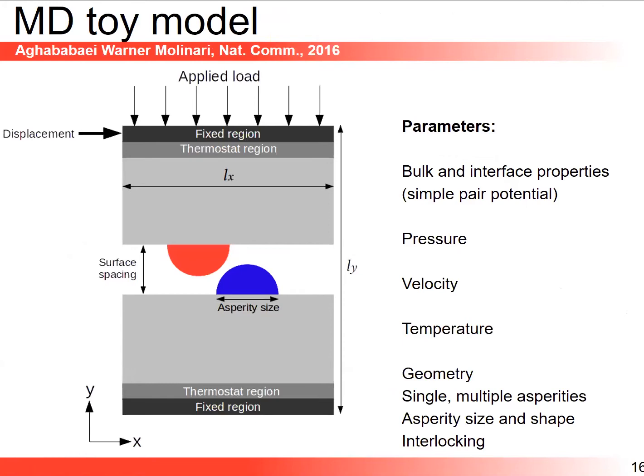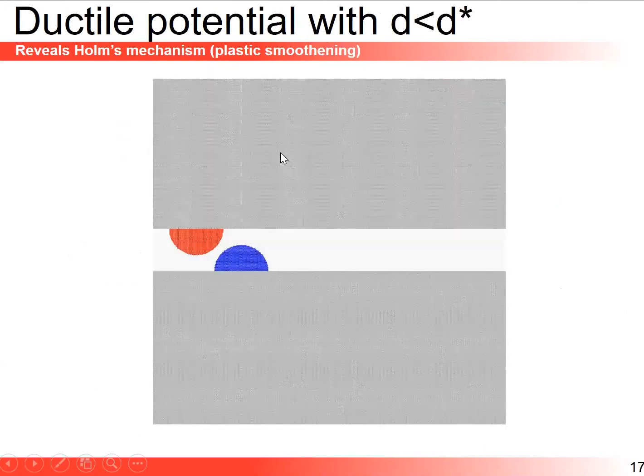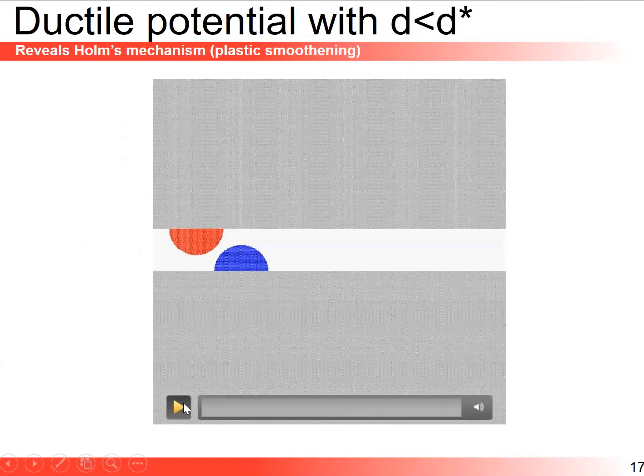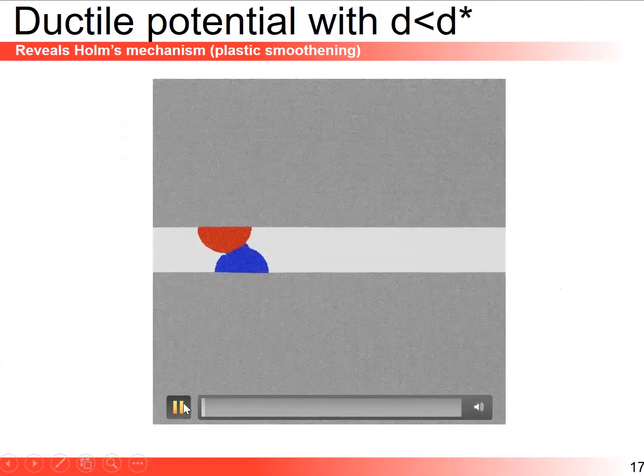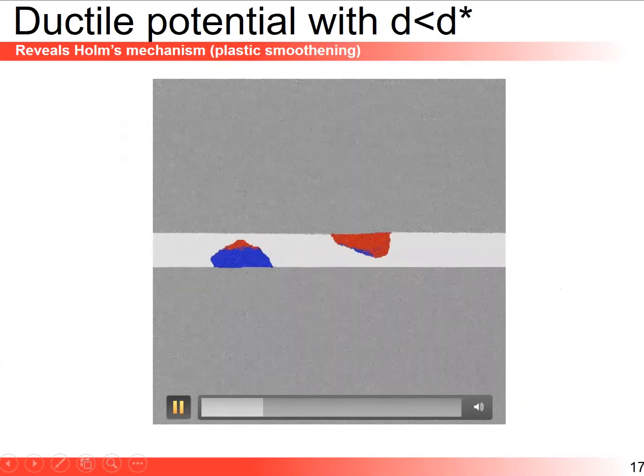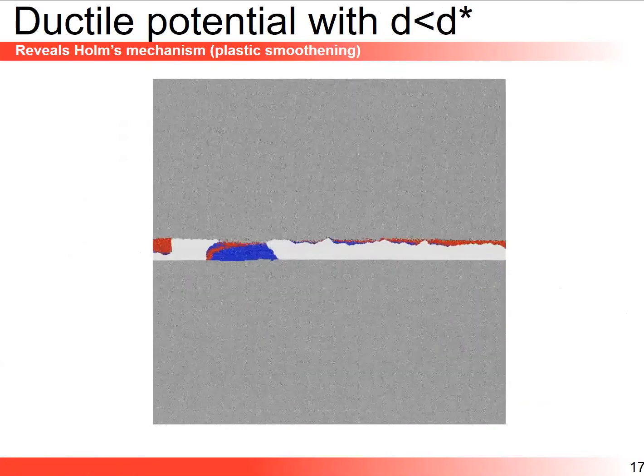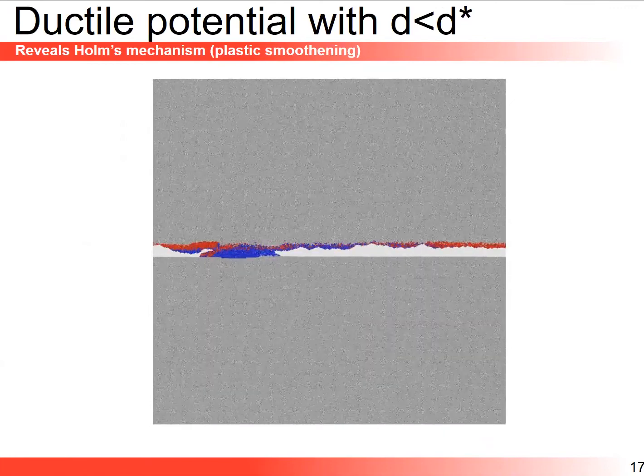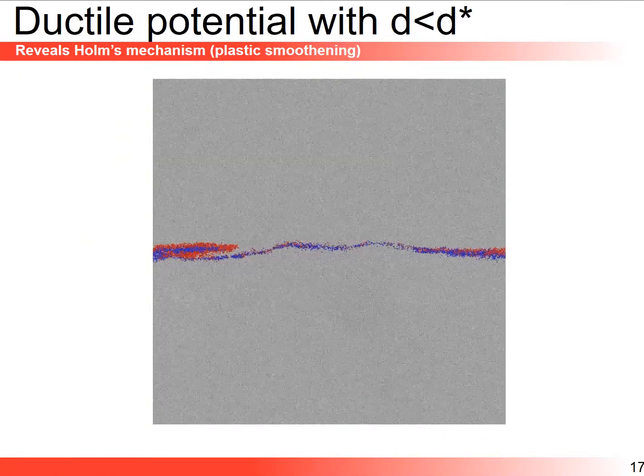So the original simulations are here. Just to illustrate my point, I'm going to show a case of two colliding asperities. The coloring is artificial, just to see where things are moving. We maintain a fixed pressure. We'll have periodic boundary conditions on the side. We apply a displacement. And what we saw is that if you develop a junction size which is smaller than this D star, we observe what everyone else had observed. That is a lot of adhesive transfer from one surface to the other. And eventually, because we maintain the pressure, we're going to close this gap, and we have not formed a debris.